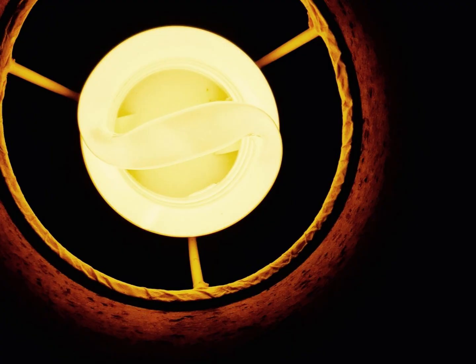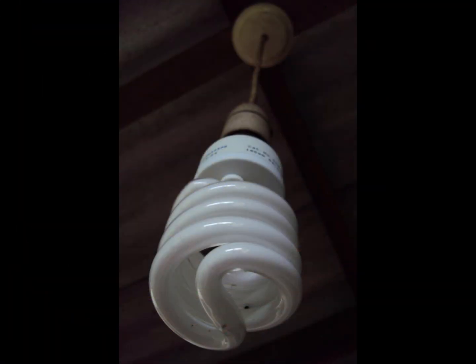For example, a 100-watt, 1,000-hour, 120-volt lamp will produce about 17.1 lumens per watt. A similar lamp designed for 230 V would produce only around 12.8 lumens per watt, and one designed for 30 volts, train lighting, would produce as much as 19.8 lumens per watt. Lower voltage lamps have a thicker filament, for the same power rating. They can run hotter for the same lifetime before the filament evaporates.